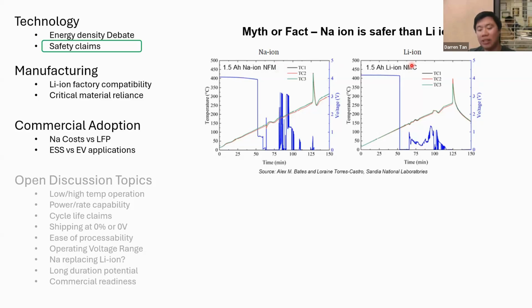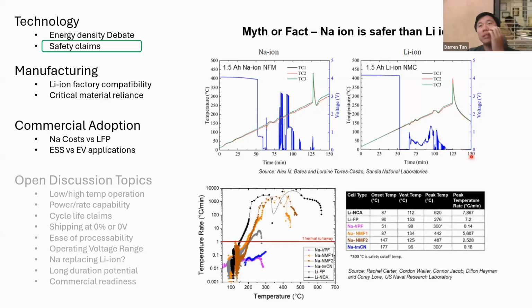Now, what about other chemistries? Another very nice study that was also recently released was from Rachel Carter's group at US Naval Labs. Here they did a similar barbecue safety test on lithium NCA, lithium LFP, and a bunch of different sodium-ion chemistries. Let me talk about the lithium ones first. The lithium NCA one was the most explosive. At around 150 Celsius or so, the separator melted and the temperature rate skyrocketed to 7,000 degrees a minute. So that's really, really hot.